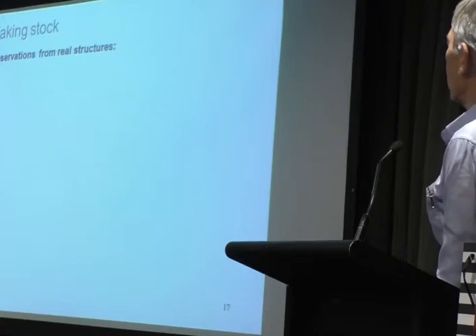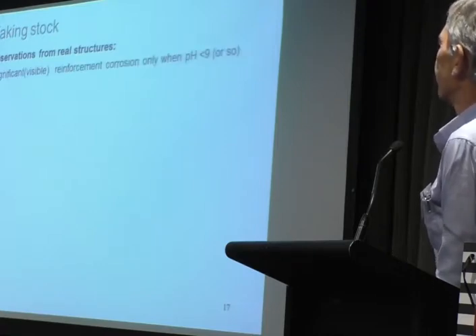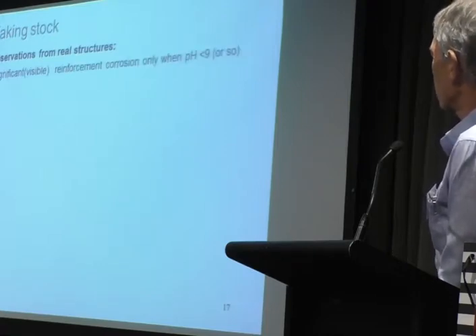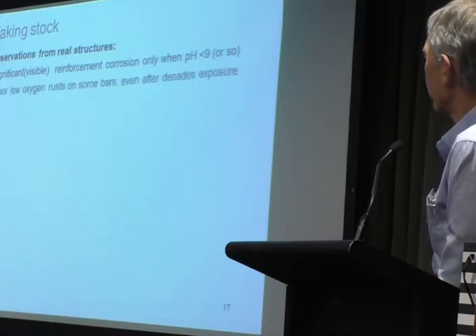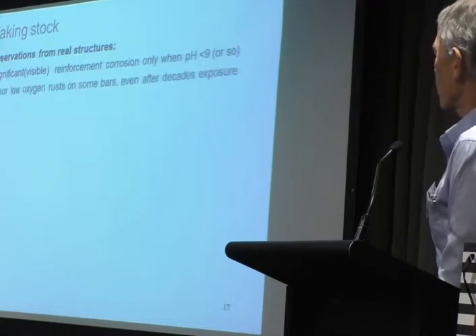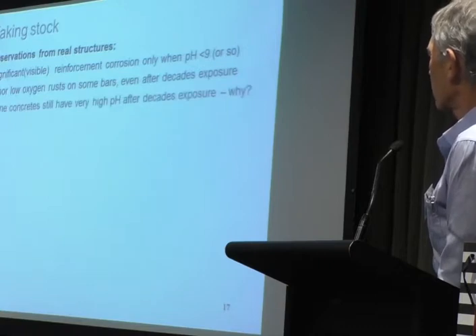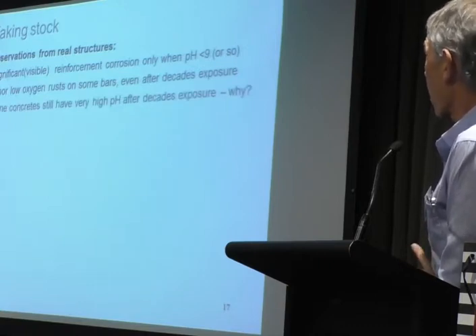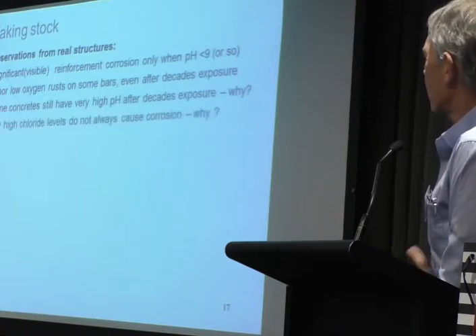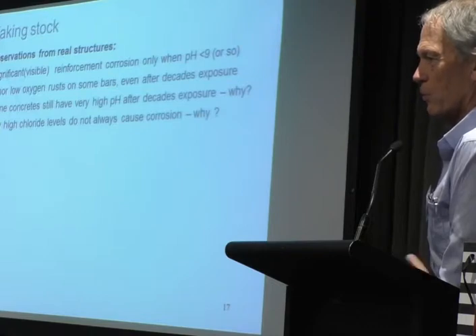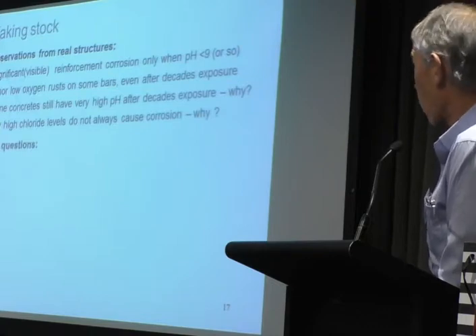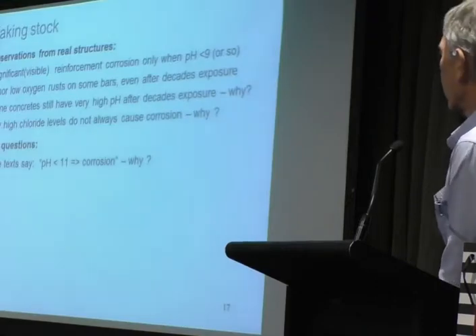Taking stock, so what have we got? Observations from real structures tell us significant reinforcement corrosion occurs only when the pH is less than 9 or thereabouts. Minor low oxygen rusts on some bars even after decades of exposure. Some concretes still have very high pH after decades of exposure. Why? Very high chloride levels do not always cause corrosion. That's what we can deduce from those cases. Again, why? More questions.